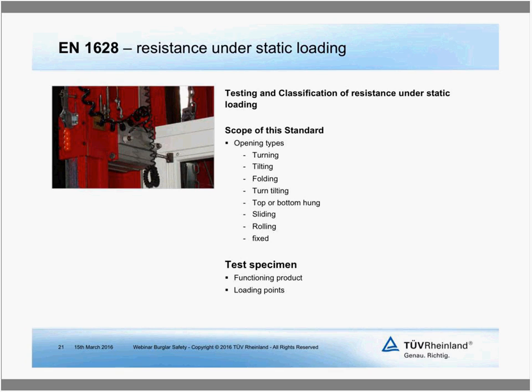Of course, it has to do with all the opening types which are listed here. This is what we call a long-term loading, long-term being more than 5 seconds. And the loads you apply are listed in EN 1627 for each of the different opening types or the groups you have specified before. To give an indication, the loads can go from 3 kilonewtons up to 15 kilonewtons. The load itself can be quite severe.